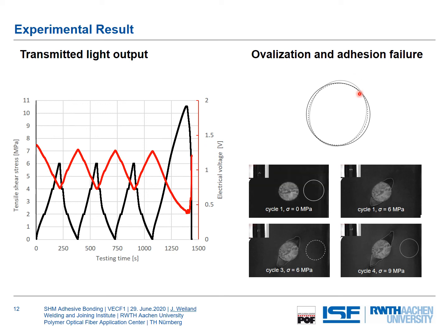The other thing I want to show, and that's also the next big thing we have to investigate, is the adhesion properties of the cladding material, which we have to optimize to have a really good connection between our cladding material and the adhesive bond. Then we guess the change in the shape will also be higher. And what we see in those pictures is debonding from the adhesive to the cladding material, exactly in that area where we have these very high stresses. During the cycles, these cracks are growing, and in the end that's also the reason why the bond fails. So that's the big thing we have to investigate to optimize this behavior.